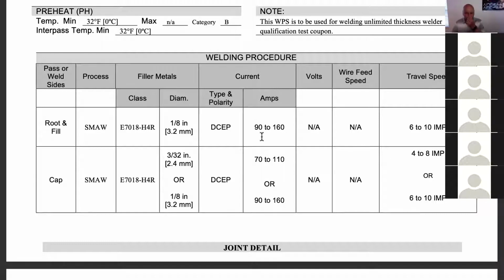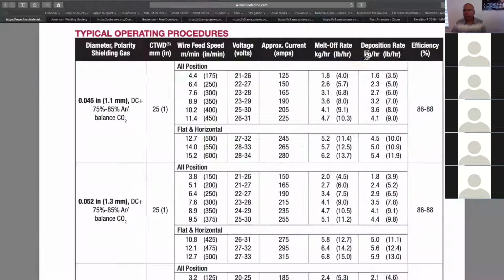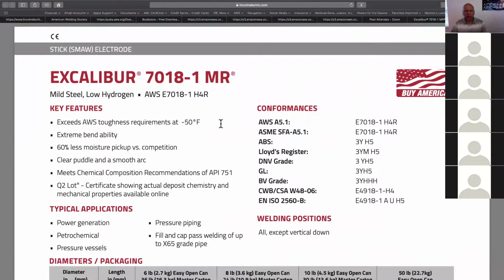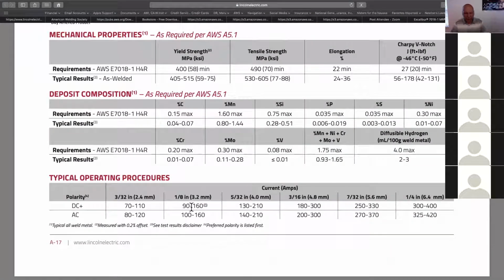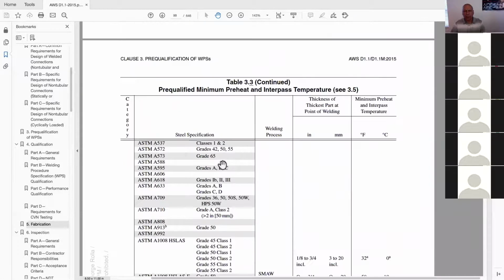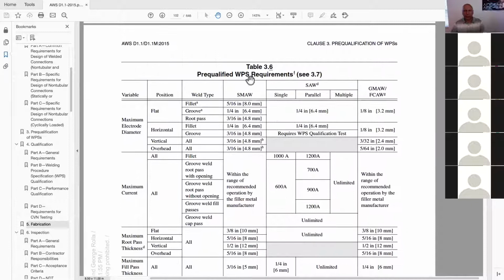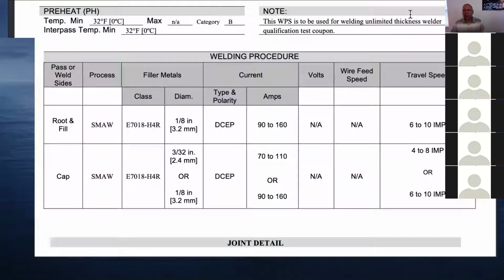Yeah, I think we use the range. I'd rather keep it 10% up or down, but we're not required. It's still pre-qualified. We can use the full range recommended by the manufacturer. And if you remember when we were doing the Excalibur 7018, it actually allowed us from 90 to 160 amps for 1/8 inch electrode. According to the tables in D1.1, that's Table 3.7. Where is that? Right here. The maximum current can be within the range recommended by the filler metal manufacturer for pre-qualified WPS. So I think that's the reason we did that.